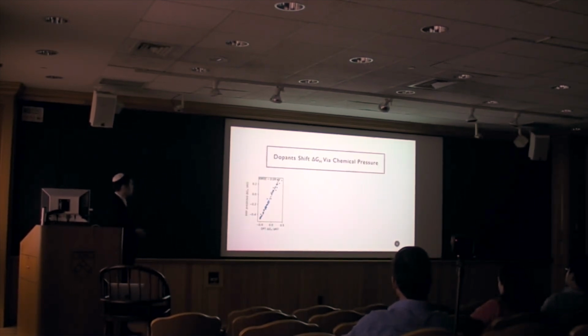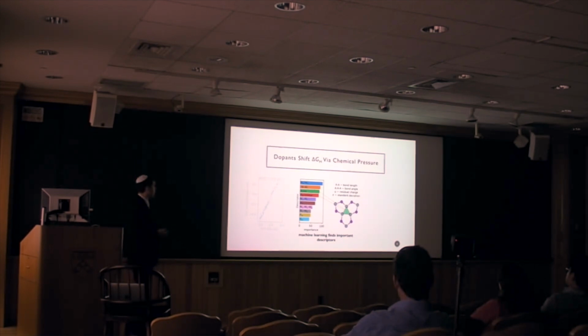Okay, so using this formalism, we fit the binding energy using a random forest algorithm. As you can see, a perfect fit would be right along this dotted black line, and we get a very good fit. And then from this model, because we're doing splitting on chemical features, we can go back in with a microscope and see what features were the most important in determining catalytic activity. And the most important features that we find are geometric features, like the average nickel-nickel bond length.